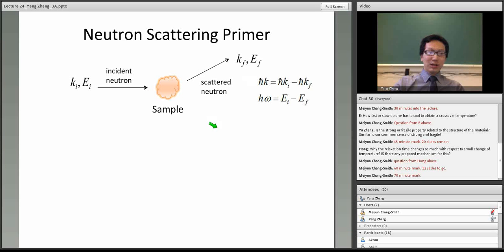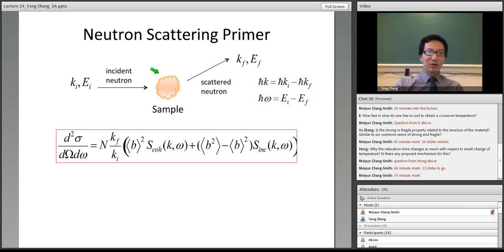So at the end of the day, for the interaction here, you can choose a Fermi pseudopotential and find out the double differential cross-section. At the end of the day, this is the only formula, a very simple formula that you need to remember. What you detect is this double differential cross-section. It's basically a sum of two terms. One is the coherent dynamic structure factor. The other is the incoherent dynamic structure factor.